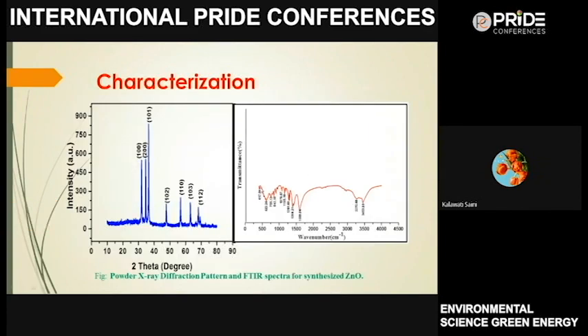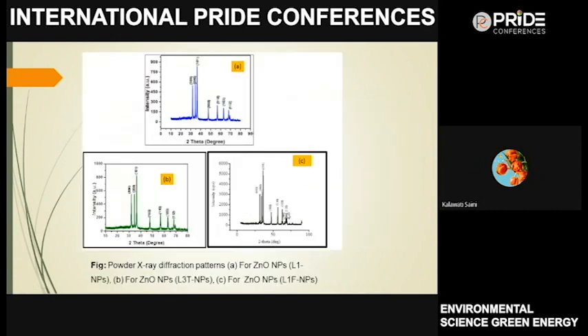This is the powder XRD pattern, which matches with JCPDS number 1451. And this is the FTIR spectra, which shows incorporation of various functional groups coming from phytochemicals present in the extract, by which the particle is coated, or we say green coated.